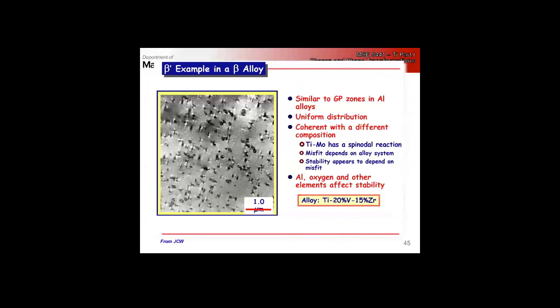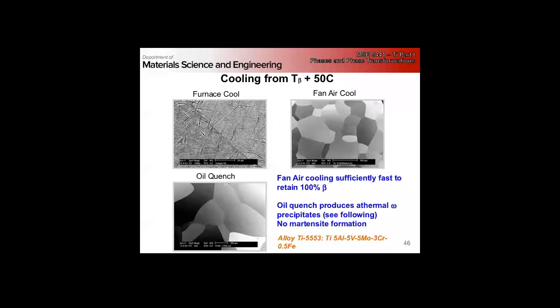Titanium molybdenum is actually a spinodal decomposition, right? And there's still a lot of research going on about what's actually happening here. What are the nucleation mechanisms? What are the stability? Other alloying elements can greatly affect the stability, how fast these can redissolve, what the critical radius is going to be, and how potent nucleation sites they are for other elements, right?